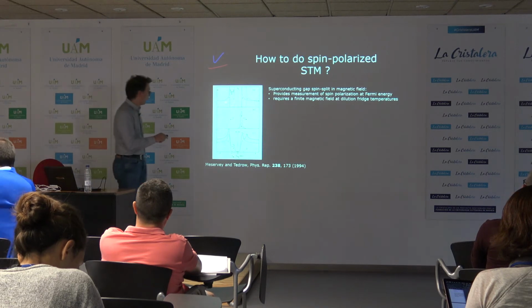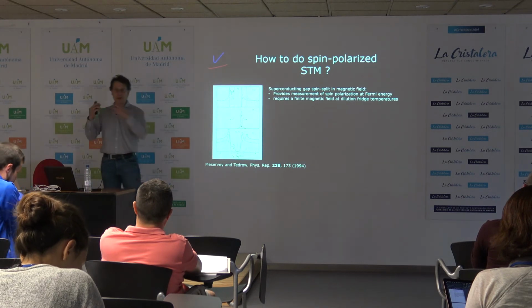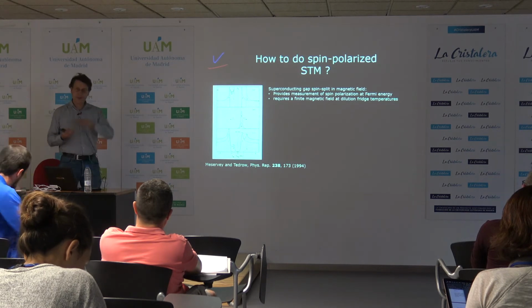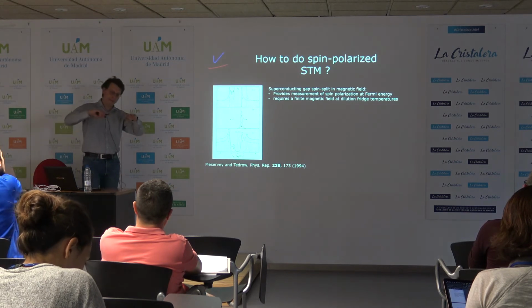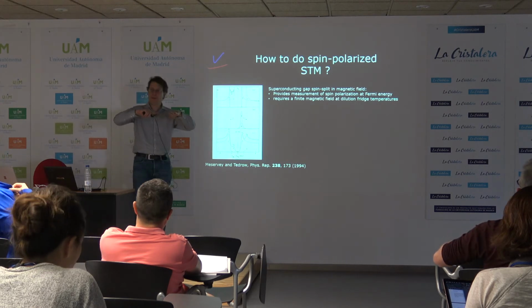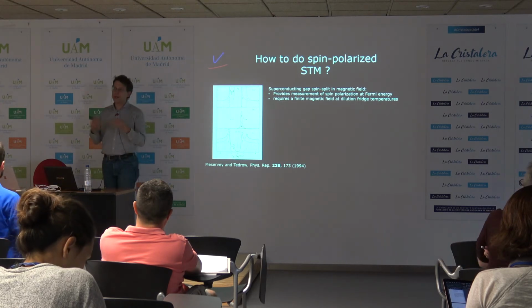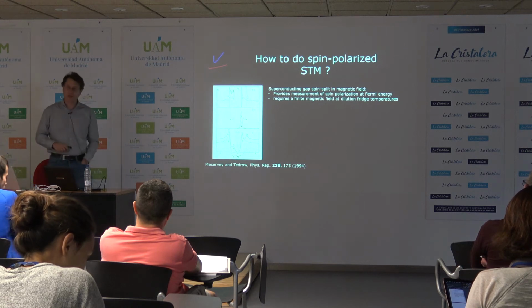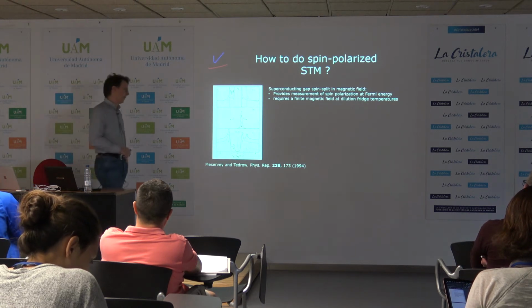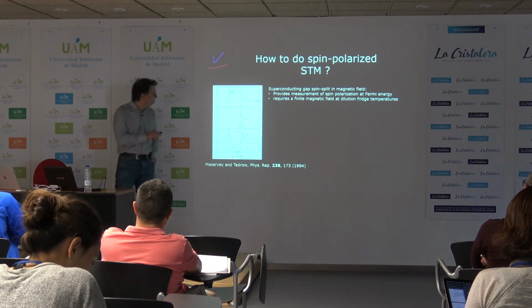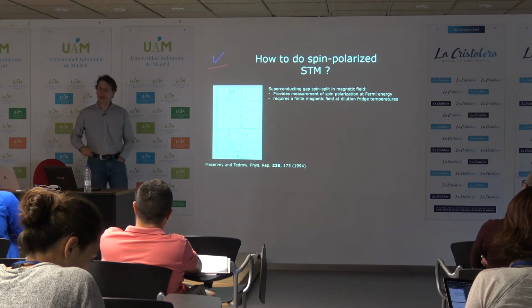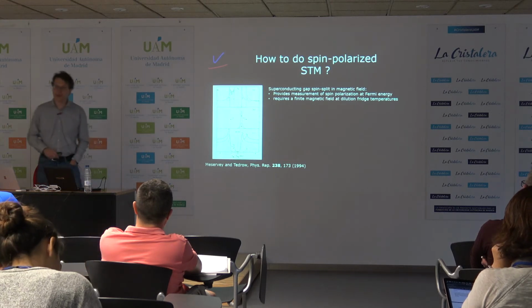The principle is you apply a magnetic field. In these planar films, if your field is in the plane, you don't get orbital screening currents, and then you can split the BCS density of states. If the spin-orbit coupling in the superconductor is sufficiently small, you can use these spin-polarized coherence peaks to probe the spin polarization of the sample.